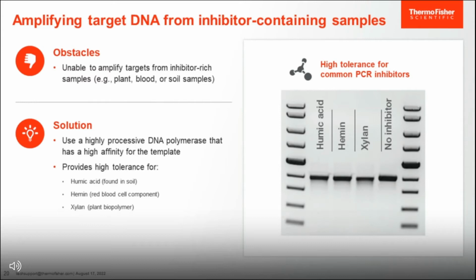So how can a higher processivity of an enzyme help in a daily PCR? If you amplify DNA from inhibitor-rich samples like plants, blood, or soil, you may have difficulty with your PCR. This is typical because PCR inhibitors are not completely removed during DNA purification. In such a case, if you use a highly processive enzyme, you can overcome PCR inhibition because these polymerases tolerate suboptimal reaction conditions. You can see an example here on the right where DNA samples were amplified with spiked known PCR inhibitors using highly processive Platinum II Taq DNA polymerase.